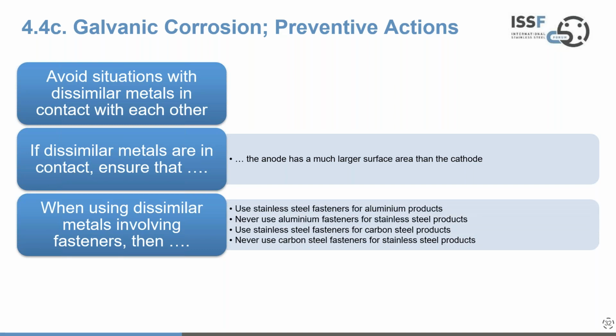And then some key rules: use stainless steel fasteners for aluminium products, but never the other way around, never aluminium fasteners for stainless products. Use stainless steel fasteners for carbon steel products, but never the other way round. And a classic example of that for people that like to go to football matches, particularly gents, because you don't have this feature for ladies at football matches. The modern football grounds, even though we can't attend at the minute, have stainless steel urinals, and in many cases they're fixed to the wall with carbon steel fittings.